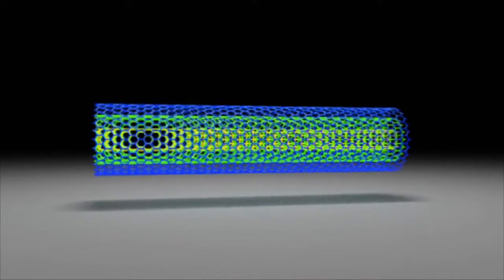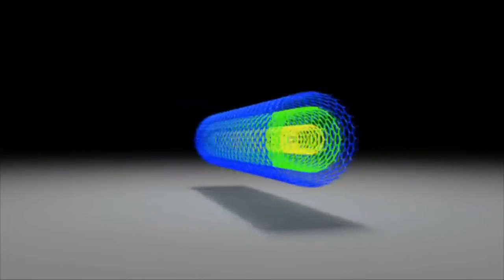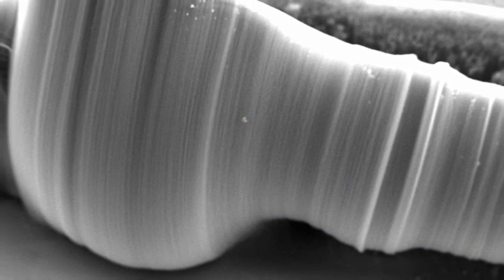The Goddard samples were grown multi-walled, so they're not just single-walled nanotubes. And they're also oriented straight up and down. The reason that the oriented samples are darker is because they're low density. Light can go in. It gets rattled around in there and it gets absorbed.